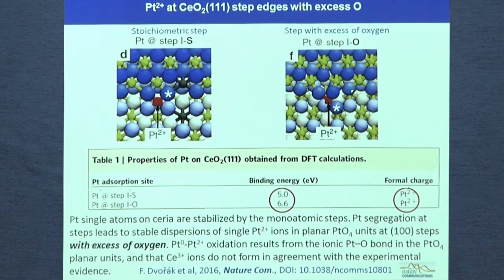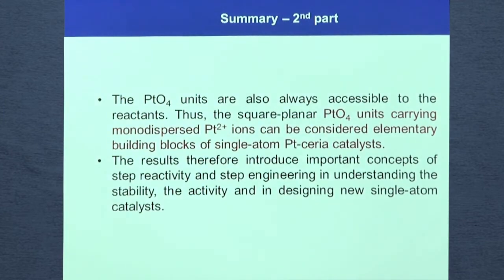Now, and again, it can be explained that we have two types of steps, stoichiometric steps and oxidized steps. If we add one oxygen at the steps, we have 5 oxygen around, and very rapidly we see that we have binding energy 6.6 eV. So again, even more stable platinum. And it shows that again the platinum 2+ is located in PtO4 units and at steps with excess oxygen. Well, this is probably too fast, but the message is that the platinum is really atomically dispersed.